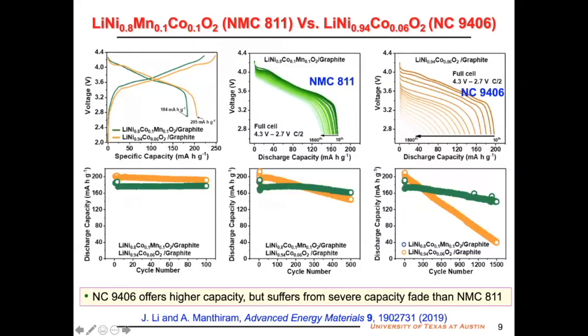I'm also going to present all the data with pouch cell, with graphite anode, not with half cell lithium metal anode, so very reliable. Here I'm comparing two cathodes, NMC 811, 80% nickel, and NC, no manganese, with 94% nickel. You can see the cyclability here. First, when you go from 80% nickel to 94%, you get higher capacity. That's why we are all interested to increase the nickel content. But the cyclability is getting worse when we go from 80% nickel to 94% nickel.